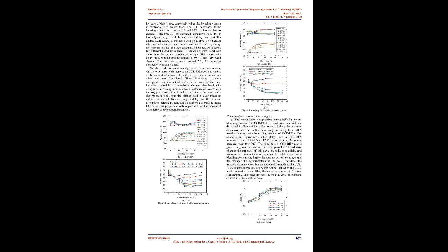Figure 3 shows the association between swelling potential of stabilized expansive soil samples and delay time. It is clearly visible that the delay time does not have much effect on the expansion of untreated soil, but the effect is obvious for stabilized soil. As delay time increases, the free swelling ratio of stabilized soil decreases accordingly. Giving an example with blending content 20%, when delay time increases from 0 h to 72 h and 144 h, free swelling ratio decreases from 84% to 60.1% and 57.2%.